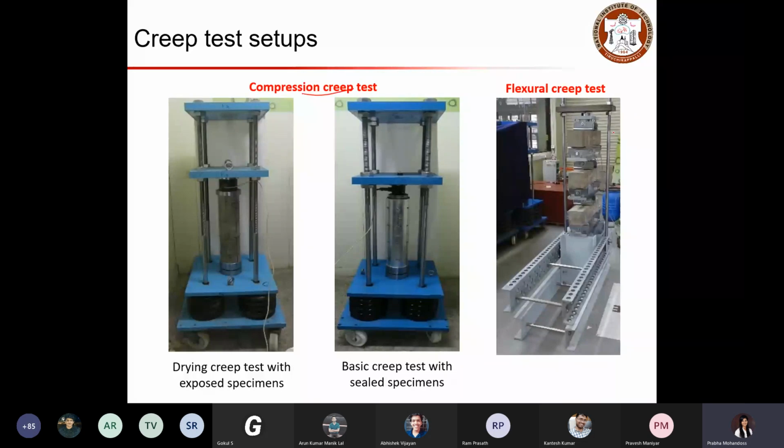And here this basically indicates the flexural creep test that we do to find the deformation due to flexural creep. So when you have compression creep, you are basically applying the axial load, and similarly you have DEMEC pins placed on the concrete surface. Here you can see the DEMEC pins placed on the concrete surface, and using the DEMEC gauge you can measure the distance between those two pins, or the change in difference between these two pins and then these two pins to get the overall deformation.